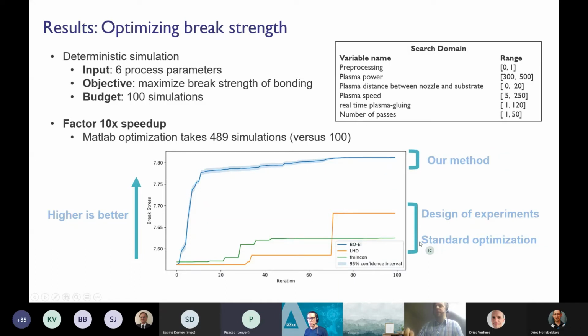But other methods, like the standard optimization method in MATLAB, you can see that it increases very slowly. So after 100 simulations, it's still much worse than our method. If you would let this run until 500 simulations, it will actually find the optimum that we also have found with our method around here. But of course, 500 simulations, it's a factor 10 slower than our method. So yeah, it's really about data efficiency and reducing the time to find the optimum.